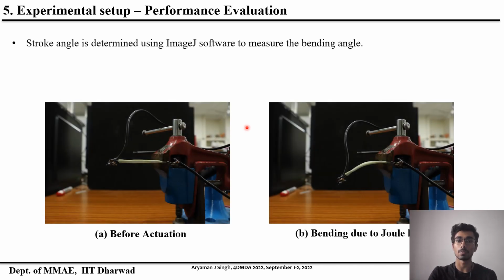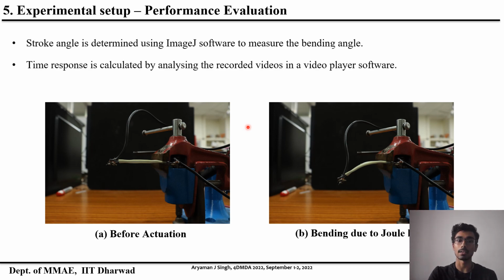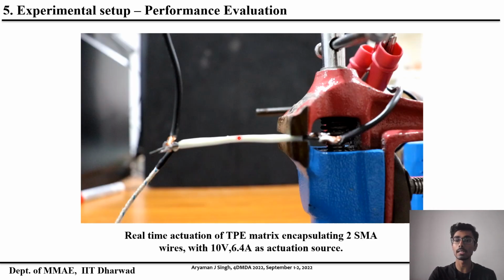For stroke angle and time response, we used ImageJ software to measure the bending angle and video player software to analyze the recorded videos to measure the time response. Here you can see the image of the actuator before actuation and bending due to joule heating afterwards. This is a real-time video of actuation of the TPE matrix with 2 equally spaced SMA wires inserted into it. The total current provided was 6.4 amps.